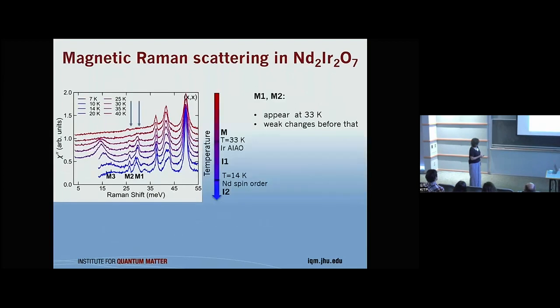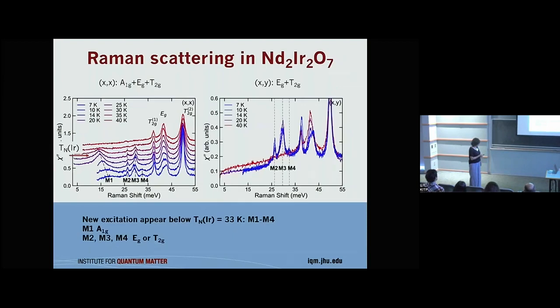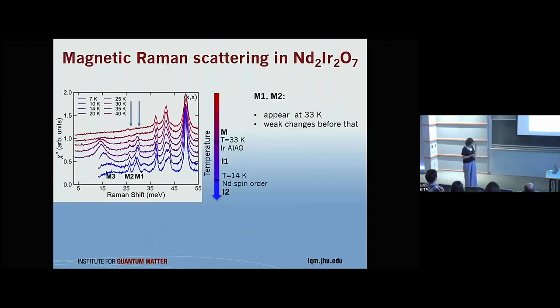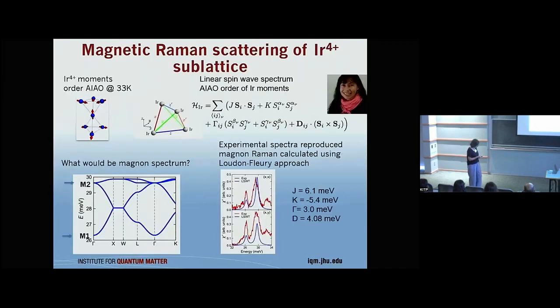So again, our interpretation is model dependent. We look at the excitations which appear below the temperature of the transition of what was expected to be all-in, all-out order of iridium. And then we say, okay, that could be a magnetic excitation. This excitation has a very strong temperature dependence, and so this was our second stage of interpretation. So then we talked to Natasha and asked if she can calculate the magnon spectrum.